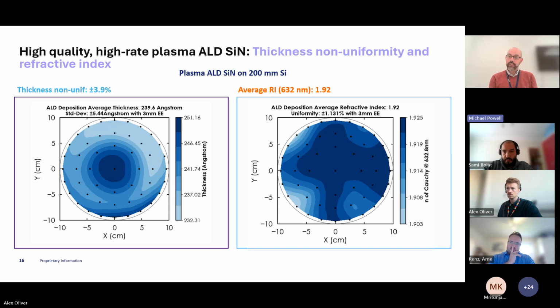And what we've developed is a low temperature plasma route that gives really good quality and really good control again. Nitrides are always a bit more challenging than oxides to get really good uniformity on, but we can get sub 4% on a 200 mm wafer, and we're getting control on the RI as well. So the RI is quite fixed for silicon nitride in ALD. 1.92, 1.93 is quite typical for RIs for silicon nitride.